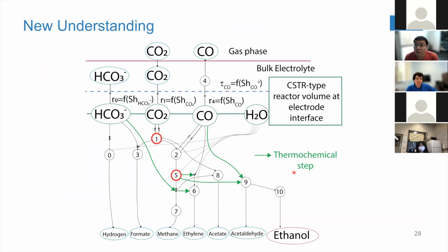And so now, out of that complex network for CO2 reduction, we actually find that there is just one mechanism that can explain the different reaction rates that you see when you change the bicarbonate concentration. If your mechanism is correct, it should be able to explain all the different products or rates that you see as you change any condition, whether it's temperature or rotation rate. So what we have done is take a lot of experimental data and use it to narrow down what is the rate limiting step in these transformations.